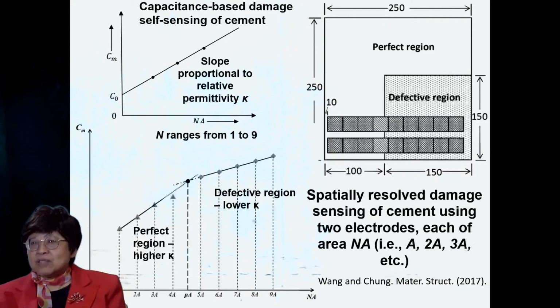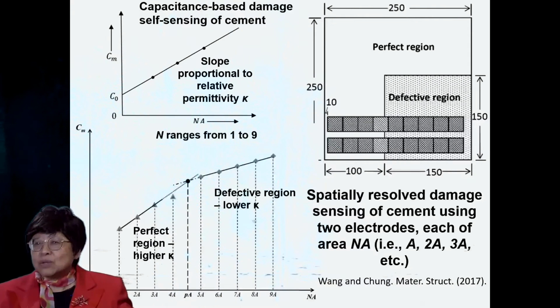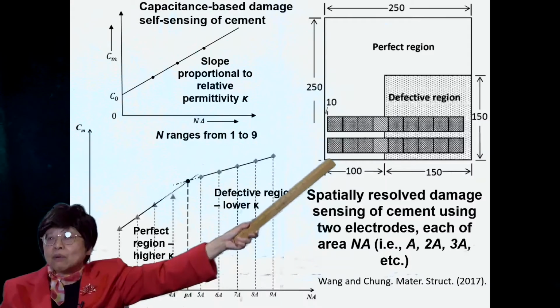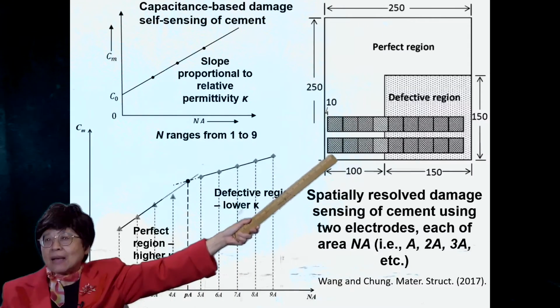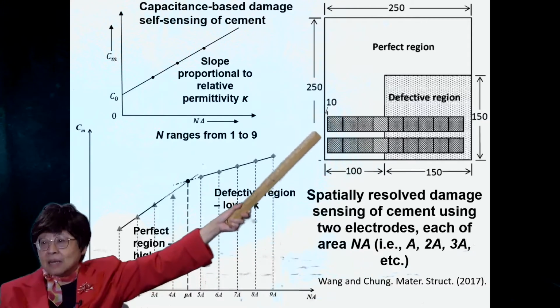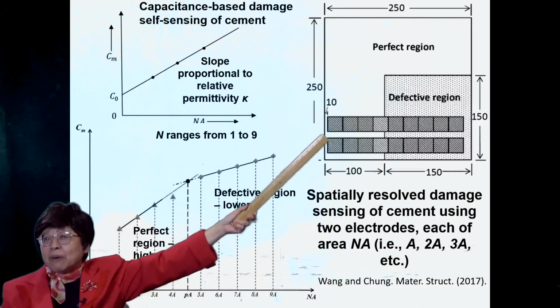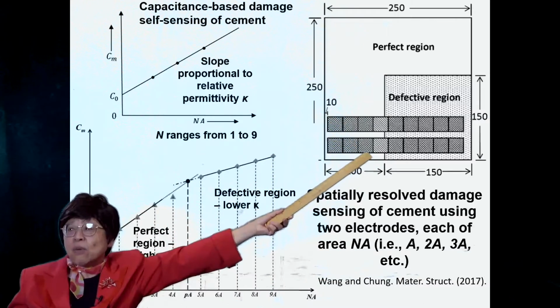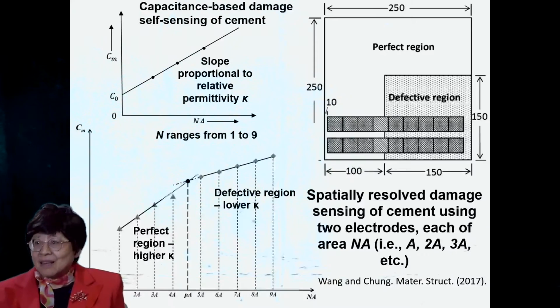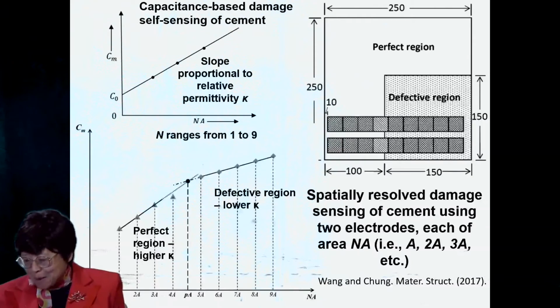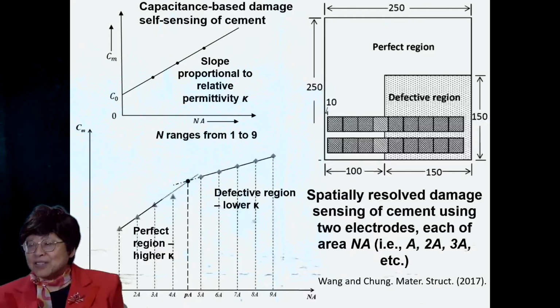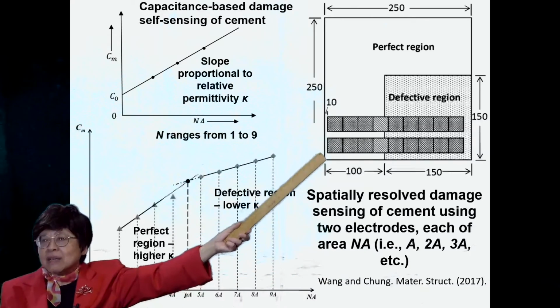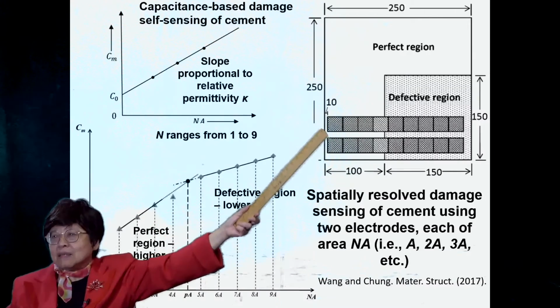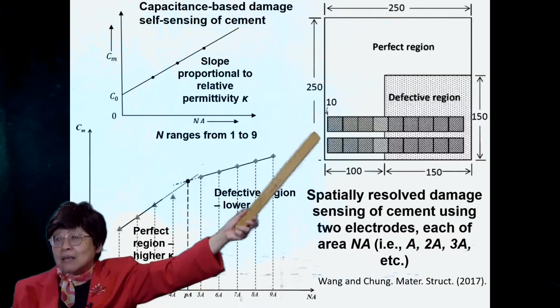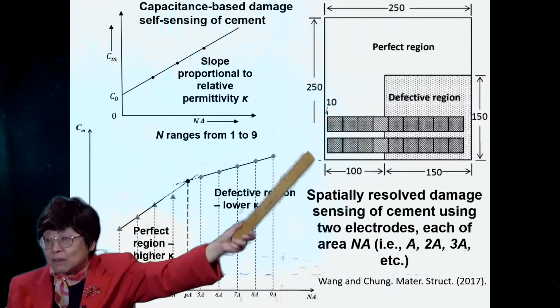And we can also do damage sensing or defect sensing for cement using 2 bars. Each is an electrode, but each bar has 9 segments in it, and again, it's coplanar electrodes. And this sample is perfect in this region, and in this square region on the right is defective, having some foamy stuff incorporated in that region during the fabrication. And we measure the capacitance using different numbers of these segments. So A, or 2A and 2A, or 3A and 3A, and so on.